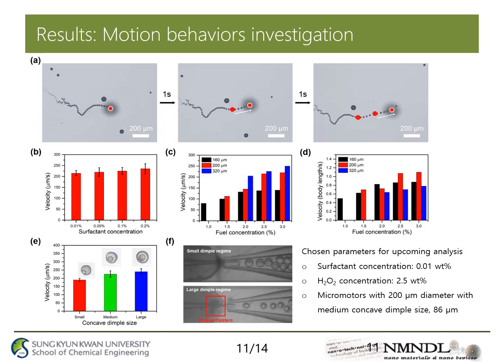Now, after we observe the motion, a few parameters have to be taken into consideration. An experiment was carried out to figure out the optimal parameters. And after all this, the surfactant concentration of the simulated fluid was tested, and the optimal concentration is 0.01% weight.